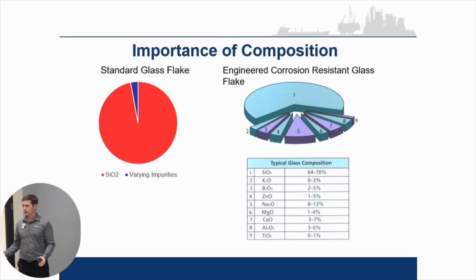The idea is in heavy chemical environments, it's not good enough to only have that tortuous path with water. You also want a glass flake and resin system that will resist and is inert to a wide range of chemicals. So the glass flake is the backbone of these coatings. The resin selection varies depending on the temperature and the chemicals and the service, but having that effective glass flake loading is what really, really makes us different.